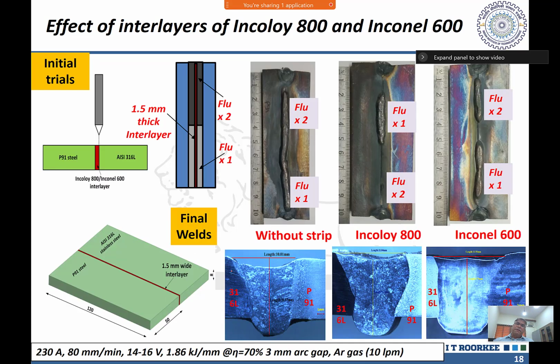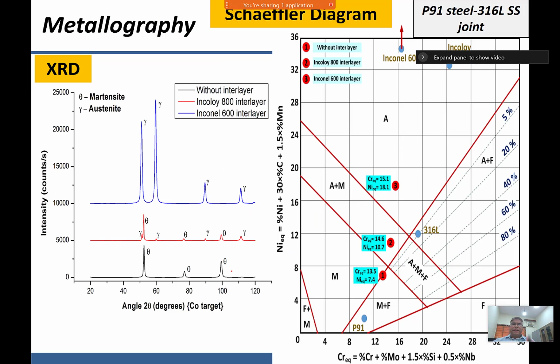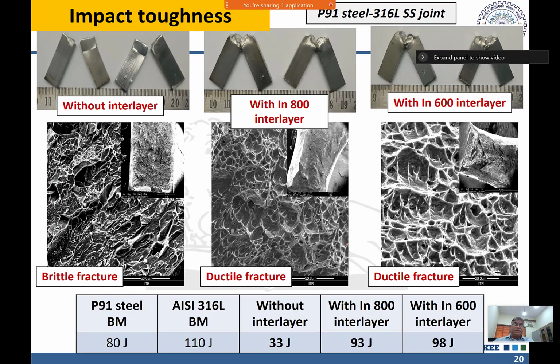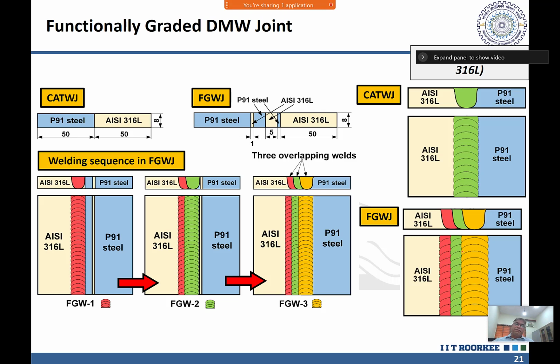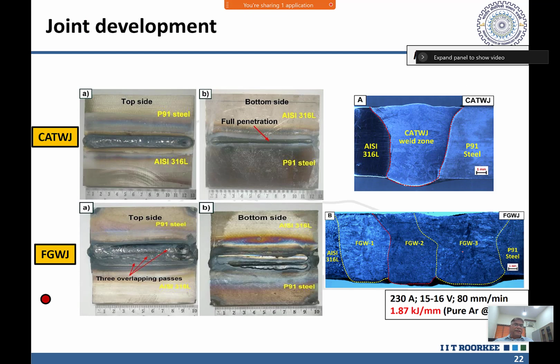Okay, so here we have used the approach of putting an interlayer for joining dissimilar metals using A-TIG welding. When we don't use any filler, it results in simply a martensitic structure, then a mix of martensitic and austenitic structure, and then an austenitic weld. And that is what we can see here. We use different interlayers, we get different kinds of structures, and that in turn leads to significant change in properties and performance. Without an interlayer, we get a very brittle weld, and when we use interlayers, we get significantly improved weld performance. Likewise we developed functionally graded weld joints also using this approach, and that again resulted in a lot of improvement in toughness, and also reduced the carbon migration tendency in the development of the weld joint.